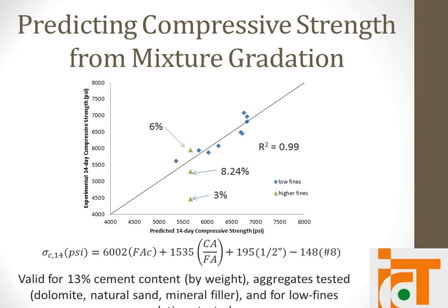One of the interesting things that we saw was that 3% fines gave significantly lower strength than any other mix, and 6% being greater than the 8%, which according to the max density curve is what should be the optimal. It's kind of expected because the gradation doesn't take into effect the cement. Using less fines than the maximum density curve says, and then adding in cement brings you close to it, whereas if we use optimal fines and then add cement onto it, we're actually dispersing the coarse aggregates. So that would be an interesting trend to see if it keeps going forward with different coarse aggregate structures.